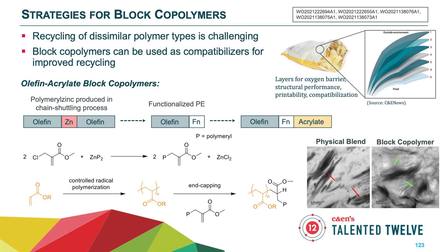And so here's one example of a block copolymer synthesis strategy that makes use of coordination polymerization, and specifically catalytic chain shuttling polymerization. As part of the catalytic chain shuttling process, we form this polymeryl zinc species, shown schematically in the middle of the slide. From this polymeryl zinc species, you can functionalize it with a functional group that you can then use to grow a non-polyolefin material such as an acrylate. And you can form an olefin acrylate diblock.